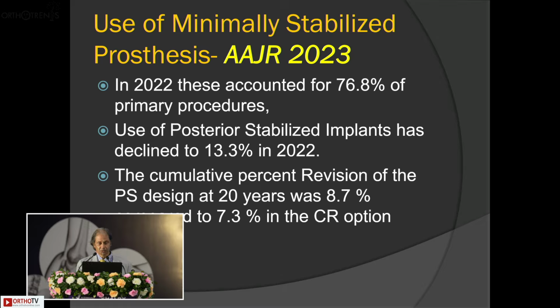So in 2022, minimally stabilized knees were accounting for 76.8%, and the use of posterior stabilizer, and Andrew had mentioned this very elegantly, the use of PS has declined to 13.3%, and the cumulative revision rate for the PS was considerably more compared to their CR counterparts. So the second most common reason for early revision and the commonest for late revision was aseptic loosening, which accounted for instability and bone loss. So this happens because of various reasons, among them malaligned, inadequately fixed options, and this really should be detected by progressive ongoing radiolucencies, which over time influence the implant position.